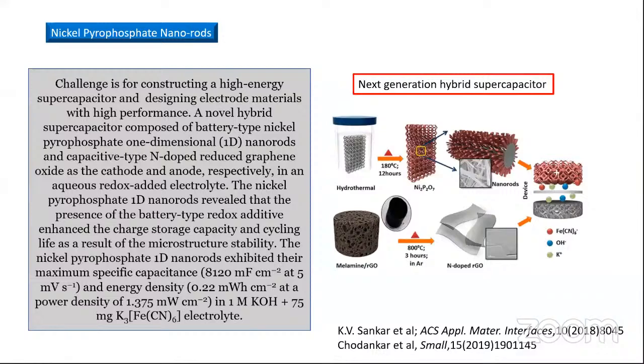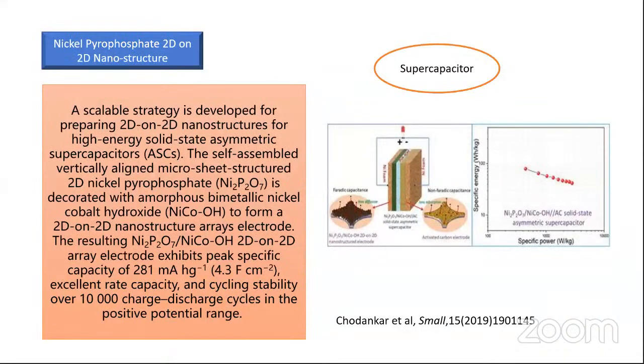Nickel pyrophosphate 2D on 2D nanostructures. Again, these are the device applications, nano device applications, and these are again used for supercapacitors. So a scalable strategy is developed for preparing 2D on 2D nanostructures for high energy solid state asymmetric supercapacitors. So the self-assembled vertically aligned microsheet structured 2D nickel pyrophosphate is decorated with nickel cobalt hydroxide to form a 2D on 2D nanostructure array electrode. So this type of array has been designed.